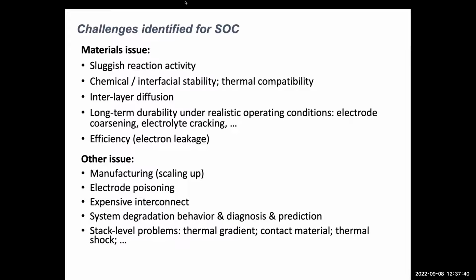The second thing is the chemical stability and also the interfacial stability, because we need to feed a very high steam concentration for the reaction, right? Under very high temperature, the reaction between the steam and the materials can happen. That can lead to some formation of insulating materials and then slow down the reaction. The next thing is the thermal compatibility. We have different layers of ceramic materials put together. That can also challenge the compatibility, because sometimes we can see some delamination between the electrode and electrolyte because of thermal shock.